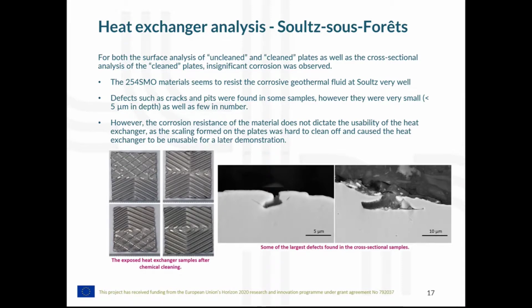We did notice some defects, such as cracks and pits, but they were few in number. And when we observed them, like on the picture there on the bottom right, they did not reach more than about 5 micrometers into the material. But as Andre mentioned previously, the corrosion resistance of the material does not necessarily dictate the usability of the heat exchanger, as the heavy scaling formation was very hard to clean off and caused the heat exchanger to be unusable for later demonstration due to the time it took to clean it. And on that note, I would like to pass the word to Béatrice.